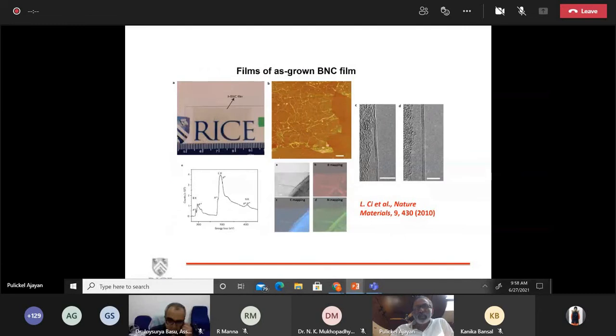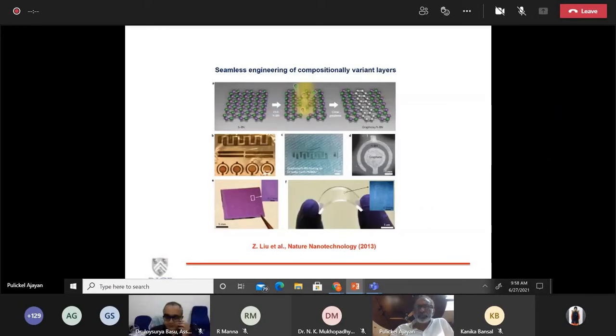And we have tried to grow many of these layers. They are highly graphitized layers, but if you look carefully in high-resolution TEMs, you can see that the domains of BN and graphene are segregated or separated in these layers. And we have also done quite a bit of engineering in trying to figure out how you can create particularly sized domains or a particular distribution of domains, and that could lead to some very interesting device ideas.